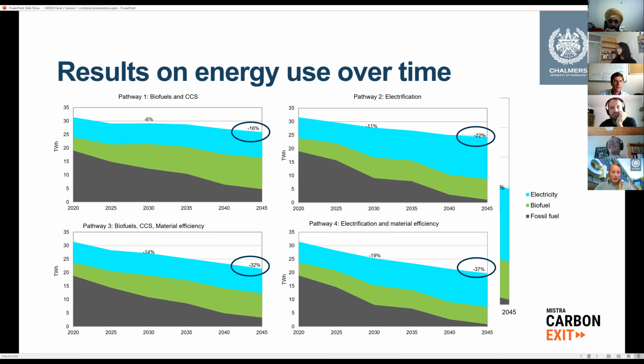And if we look at how the different energy sources are used, we see that the biofuel use, which is currently mainly used in the transport sector in Sweden, as well as in some asphalt, cement, and timber production, is set to expand, with the overall share increasing from about 15% of total energy use at present to 30% in the electrification pathways, and even up to 40% in the biofuel pathways. And the electricity use is almost constant in the biofuel pathways, but doubles in the electrification pathways, reaching a share of around 65% in the electrification pathways.